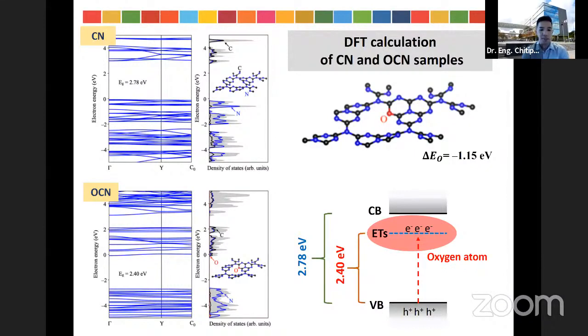And this can be seen that the valence band of the graphite carbon nitride and oxygen-doped graphite carbon nitride was mainly contributed by the nitrogen atoms, while the carbon atoms showed a big contribution for the conduction band. And interestingly, the doped atoms of oxygen in the oxygen-doped graphite carbon nitride structure generate the mid-gap state level around here. You can see in the right one is the oxygen atoms. The generation of the mid-gap state level results in the decreasing of the energy band gap of the oxygen-doped graphite carbon nitride sample. And also the DFT calculation can confirm the new formation of the trap state by observation in the ELF pattern.